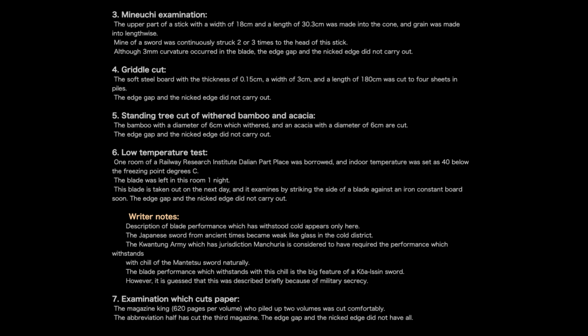Test 7. Cutting 2 books, volume of 620 pages, no breaking, no bending. The strongness of Mantetsu is the same as a koto iron, 0.5 to 0.6 of carbon, in the steel. This sword was created by researches of Dr. Kazuharu Kusaka: a pipe of iron put into a steel pipe, mechanically welded together, then forged, then hardened in an electrical furnace. This modern and scientific new Japanese sword was not forged by a swordsmith.